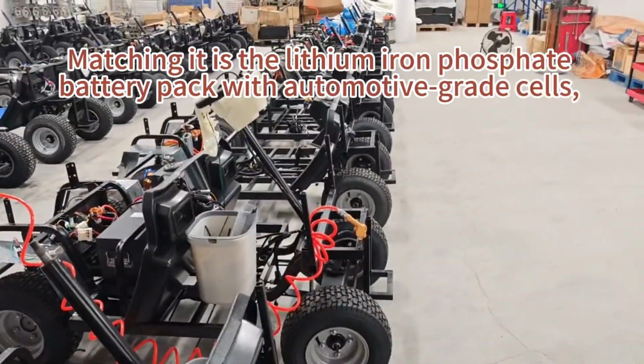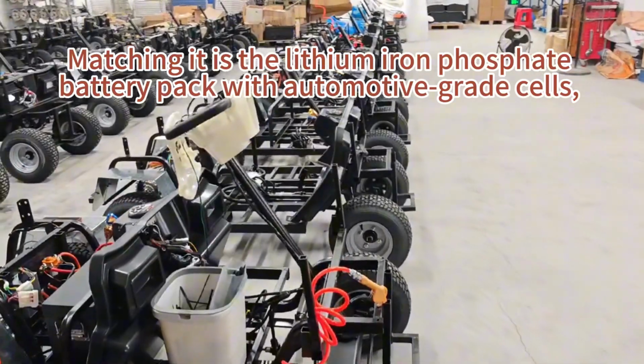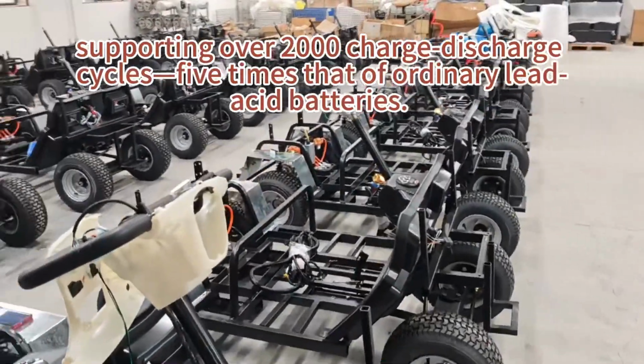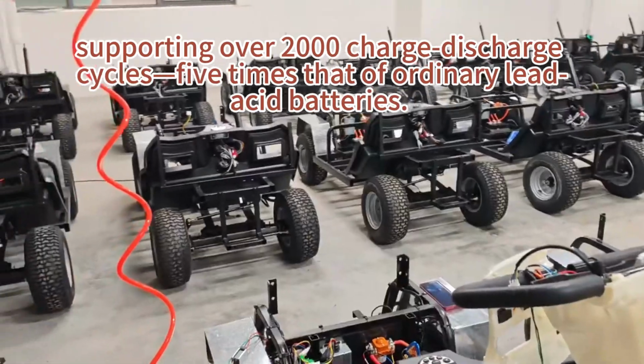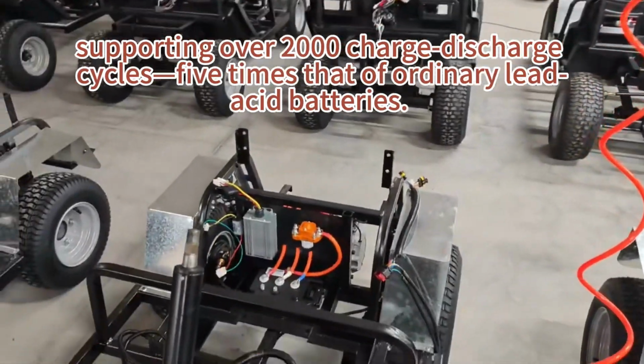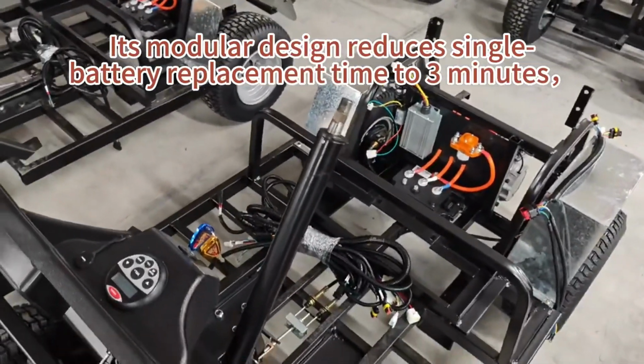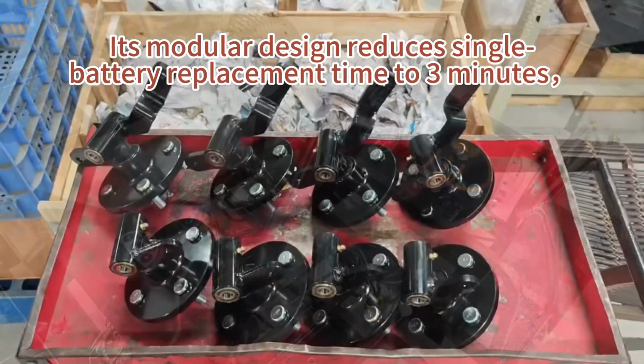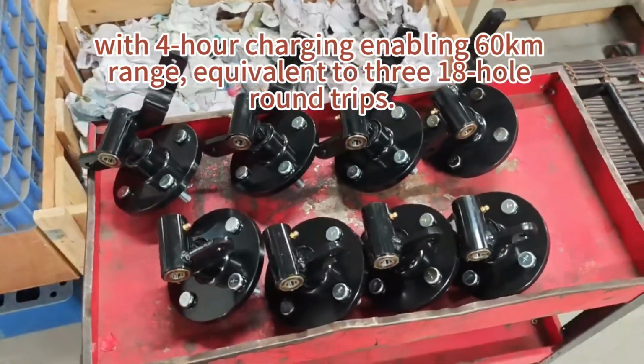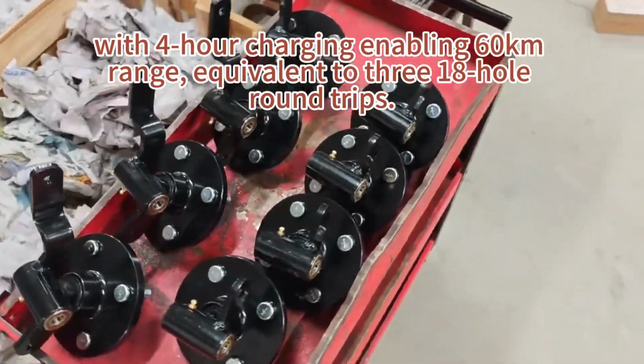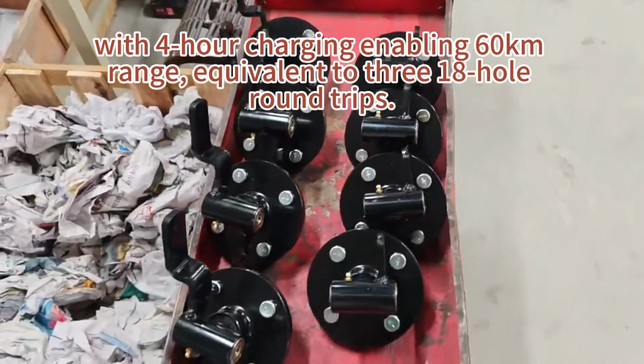Matching it is the lithium iron phosphate battery pack with automotive-grade cells, supporting over 2,000 charge-discharge cycles, 5 times that of ordinary lead-acid batteries. Its modular design reduces single battery replacement time to 3 minutes, with 4-hour charging enabling 60 km range, equivalent to 3 18-hole round trips.